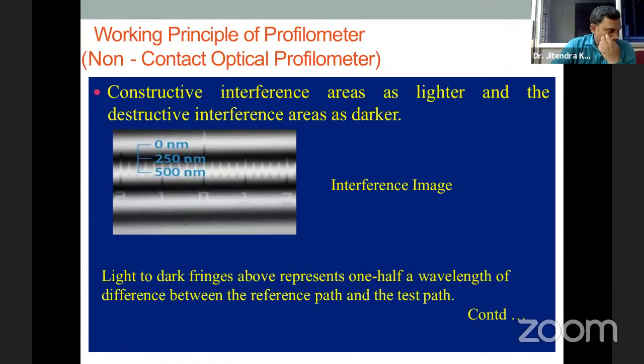This profilometer is basically used to give you the three-dimensional structure and all types of surface roughness: Ra, Rz, Rsq, Rt. You can also calculate the step height, that is, the coating thickness to some extent, but the same image gives you a better picture of the coating surface. In coating analysis, you erode some coating material from the substrate, and then it makes this type of step. What is this step height? You can calculate that with this 3D optical profilometer, and it can also give you the average thickness of your coating.